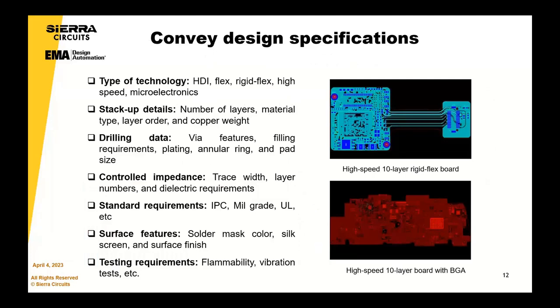Some of the critical data we require early on so we can launch into production quicker: the type of technology — whether it's HDI, Flex, FlexRigid, or micro-electronic — helps us determine which facility, process, and equipment sets to use. Stack-up details are critical: number of layers, material, layer order, and copper weights. Engaging early allows us to help drive costs out of your design. For example, designers often put double and triple ply constructions into their designs, thinking about dielectric separation and resin-to-glass ratios. But each sheet of prepreg or layer can be up to 15% of the overall cost, so we may suggest a larger or thicker core and a different prepreg instead.